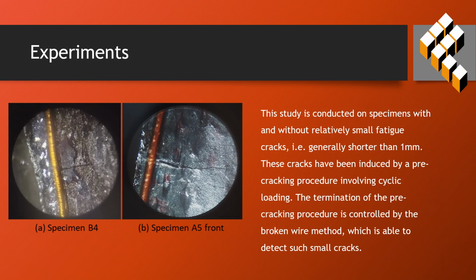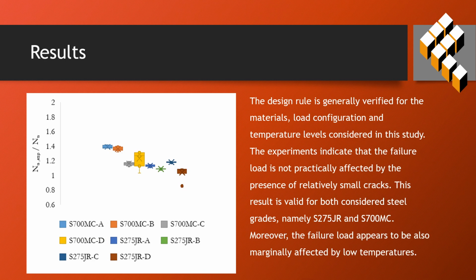The study is conducted on specimens with and without relatively small fatigue cracks, which are generally shorter than 1 mm. These cracks have been induced by a pre-cracking procedure involving cyclic loading. The termination of the pre-cracking procedure is controlled by the broken wire method, which is able to detect such small cracks. This slide summarizes the test results.